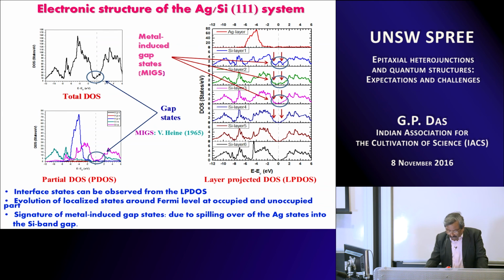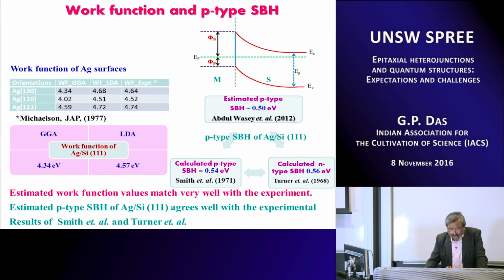We have done a detailed study of this kind of silver silicon interface. I am only going to show you the results, namely the work function values for silver 100, silver 110 and silver 111 using LDA and GGA, and they match reasonably well with the last column, which is experiment. This is the LDA value, this is the GGA value. And here are the values for the Schottky barrier height: the p-type Schottky barrier height is 0.54 electron volt for the silver silicon 111. And obviously, if you subtract from the silicon band gap of 1.1, you get 0.56 electron volt, which is the n-type. So you can see the p-type and the n-type Schottky barrier height, and this matches very nicely with experiment.